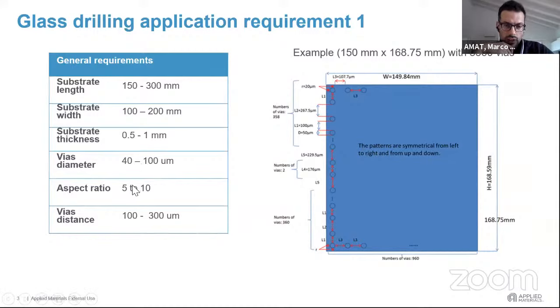So the aspect ratio ultimately can go as high as 10. So this is the diameter to thickness ratio. With the via distance, that can be from 100 to 300 microns. So this is an example of the pattern, and this normally would go all around the substrate.